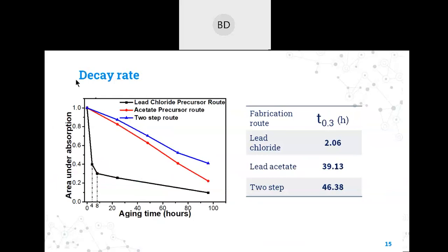And we have calculated the decay rate. If you see the decay rate for the lead chloride route, it degrades very fast. Even for 30% degradation in absorbance, it takes only 2 hours. But in the case of lead acetate and two-step films, it takes around 40-45 hours to degrade to 30% of the absorbance. So from here, we can say that the chloride route is degrading much faster.